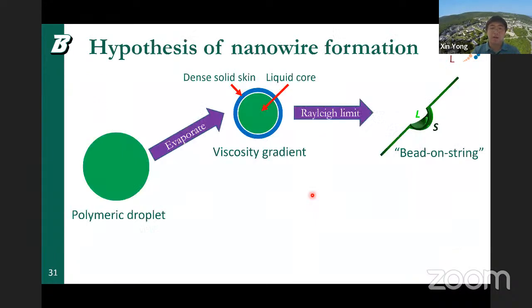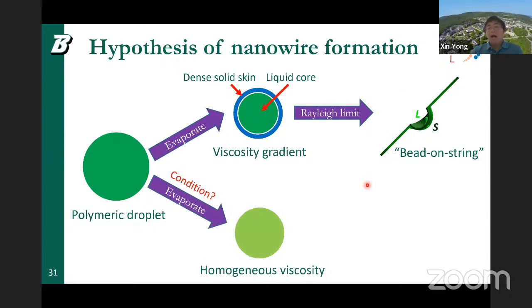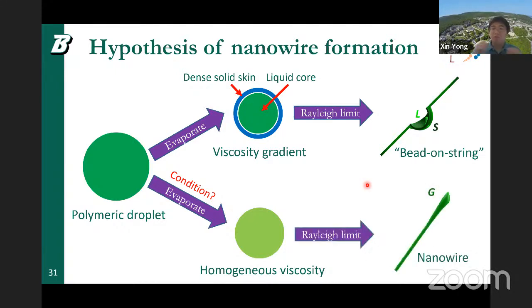So this droplet is going to be electrified. So the hypothesis is that typically you only form these anisotropic beads-on-string structures, because when your evaporation happens, you're going to get a density gradient, which translates to a viscosity gradient. And so you get a liquid core and then a dense shell. And so this liquid core is going to migrate faster under the electrohydrodynamic deformation. So that will lead to this string formation attached to a center mass. Now, what happens if we can potentially create a droplet that has a very homogeneous viscosity increase upon the time of deformation? And so that should give us a uniform nanowire, because that deformation is now going to be carried out on the entire droplet.